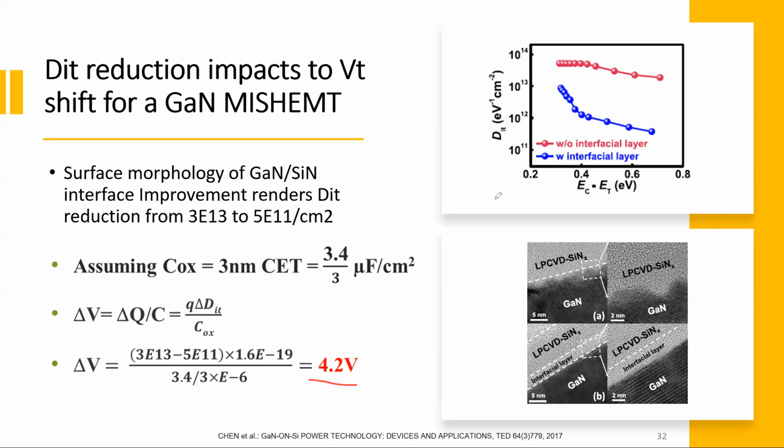All right. So this reveals how important it is that the interfacial surface has to be repaired. Here we repaired the smoothness, but here is just a defect. Here they make it less rough. See, here is wow, rough, and here you make it very flat. Nice. Even the physical change could change your defect by 2 orders of magnitude. That's what gallium nitride people saw.